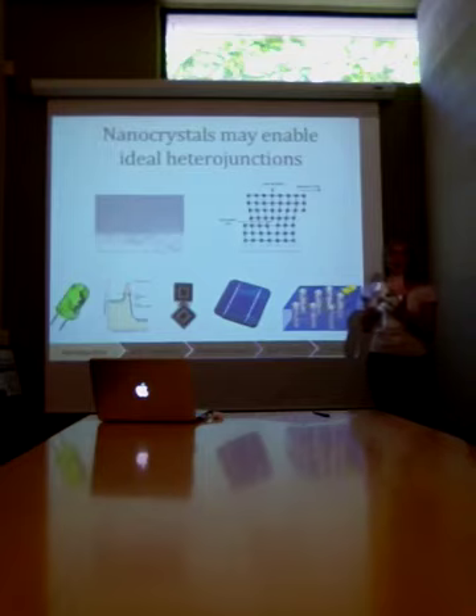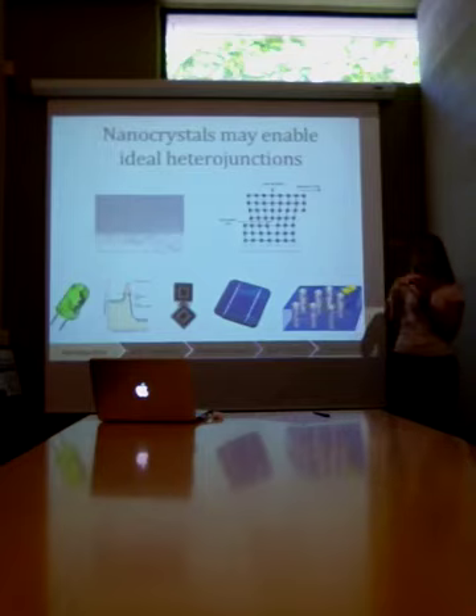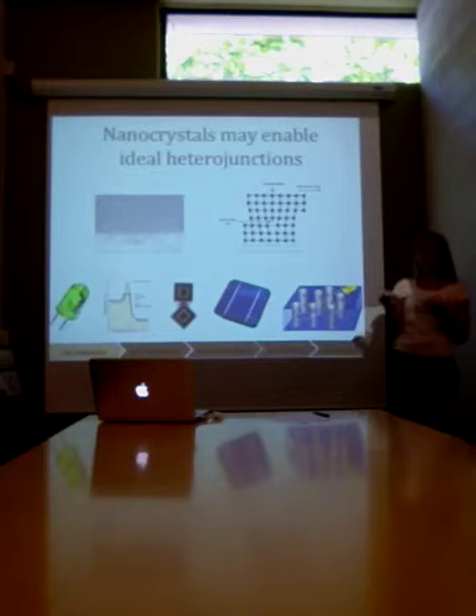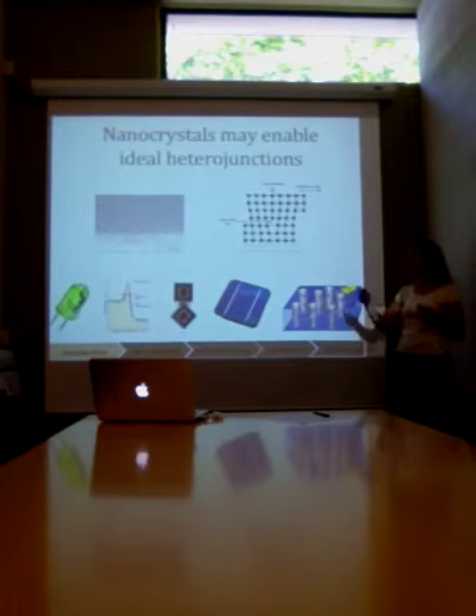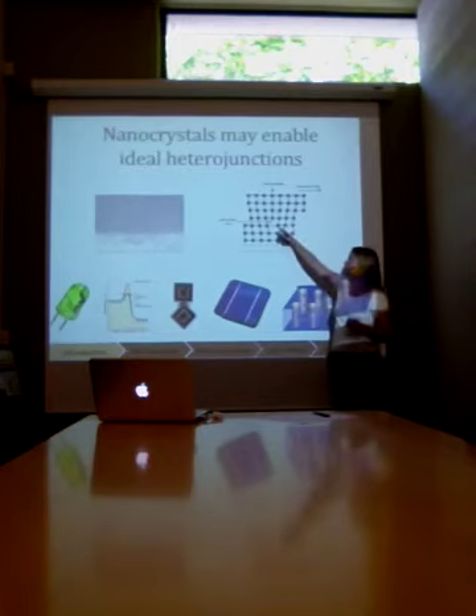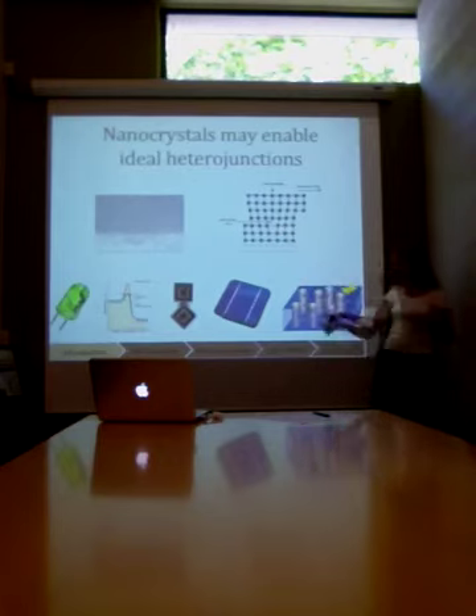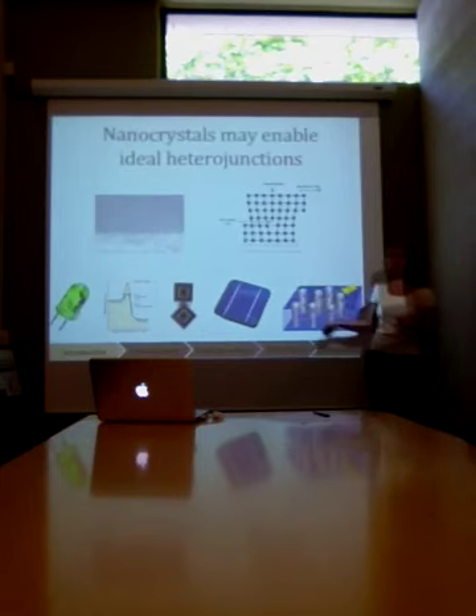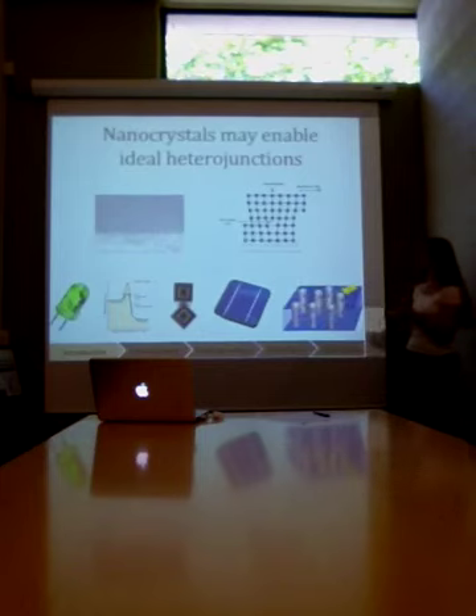But no two lattices have exactly the same lattice constant. And that means that when you bring them together, there's going to be lattice strain due to one lattice being a little bit bigger than the other one. This strain is relieved over some characteristic distance in a misfit dislocation, where one bond is left hanging. And this misfit dislocation degrades the performance of any of these heterojunctions because it's a defect at our interface.